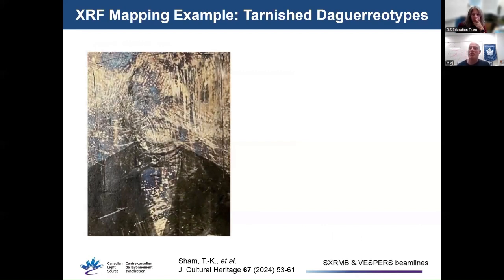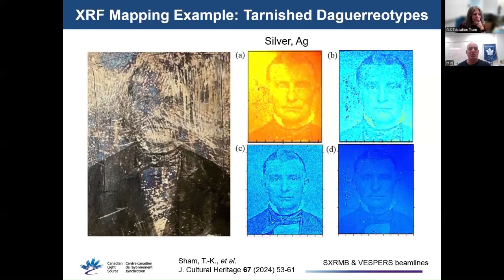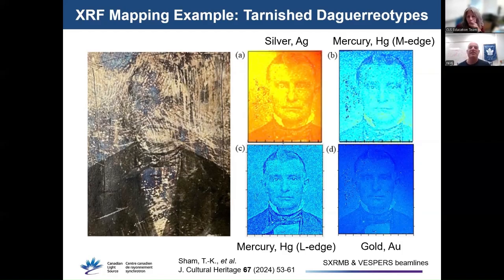Sometimes it's actually helpful to try fluorescence from different elements to see which element best reproduces the original image. In this case, silver and mercury fluorescence were attempted on one beamline with mixed results, but using a different wavelength of fluorescence for mercury on another beamline produces an improved result. And they also tried gold on a second beamline as well. And the gold image doesn't have really high contrast, but it actually looks quite good. And you can tell the bottom two maps were taken on a different beamline because they are slightly different size than the top two maps.